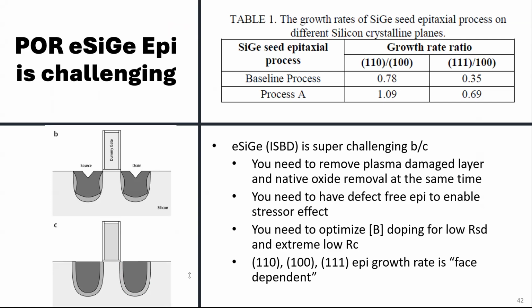This is just schematics. And then the growth rate for each surface is different. You look at the growth rate, right? In the 110 and 111, no matter how you tweak it, they are different. That's the message. Here, this guy tweaked away, so it's close. But 111 to 100 is very poor. So no matter how you tweak it, right? And so this is where the hidden jewel of a foundry is, how they perfected their source drain growth. That's what I call a solid baseline. If you don't do this process well, you're screwed.